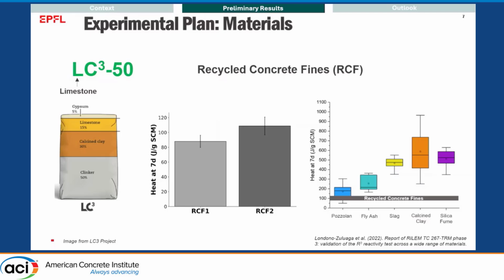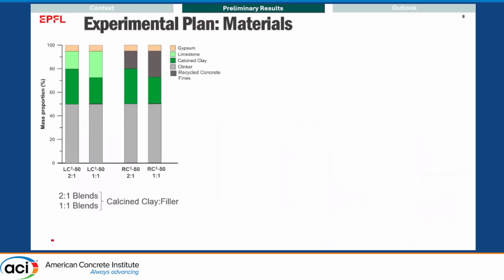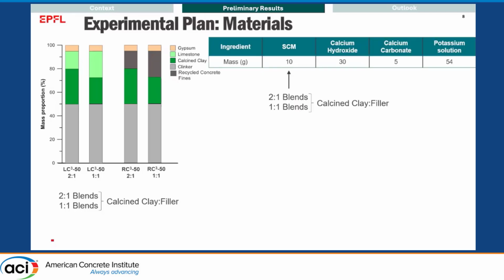So what we decided is that I'd use this as a replacement of limestone in the LC3 system. And if I'm replacing the entire limestone in LC3, I should probably call it RC3, right? So in RC3, R refers to the recycled concrete fines. The proportions of the mixes are LC350 and RC350 with two different calcined clay to filler ratios. As you can see here, one is the 2:1 blends and the other is the 1:1 blends. In the R3-Reactivity test as well, instead of the individual SCM, we put the entire blend in itself, both the calcined clays and fillers in their respective ratios, and we do the same for the compressive strength and look at the correlations in the results part.